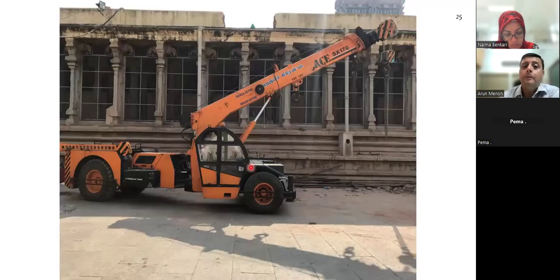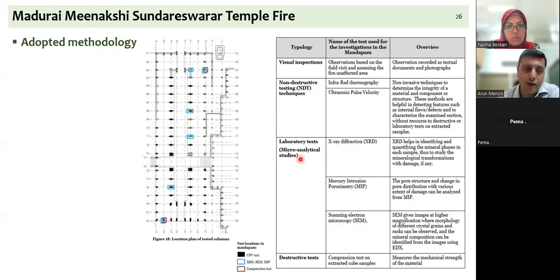And then you can see an attempt to cushion the ends of the other structure from any imminent collapse. The sizes of the columns, the sizes of the stone members were such that the use of heavy equipment was necessitated to even clear debris, and therefore these had to be operated at low velocity, at such low speeds that the vibrations do not get transmitted, but work could not progress without the use of heavy machinery and heavy equipment.